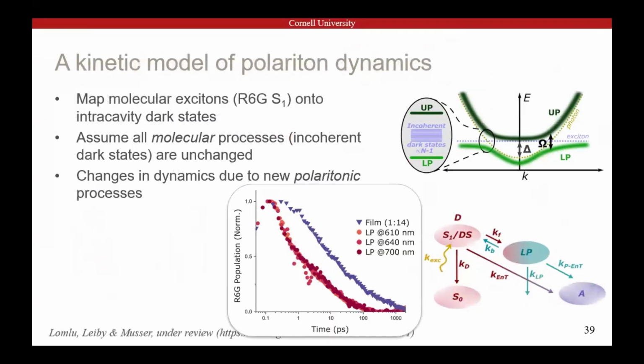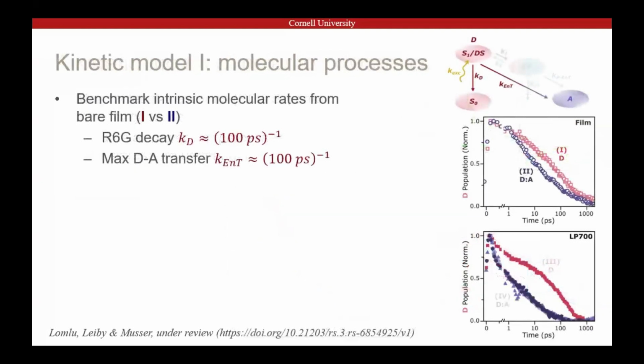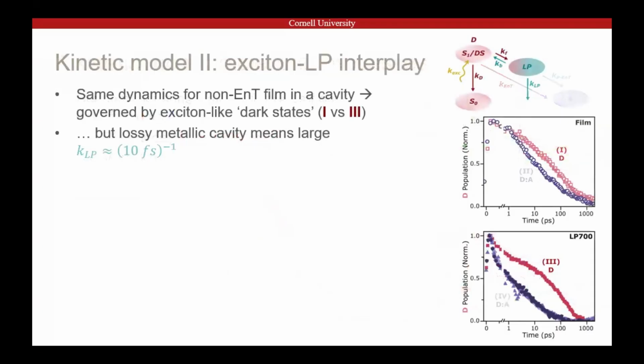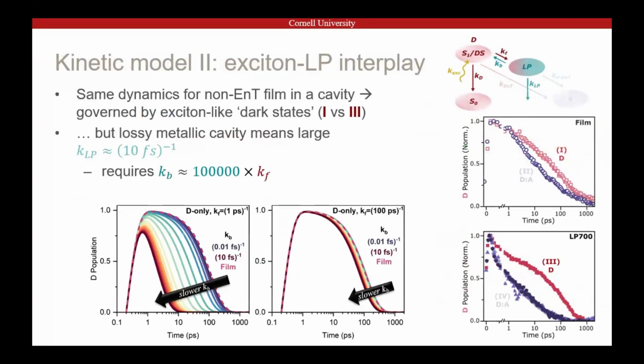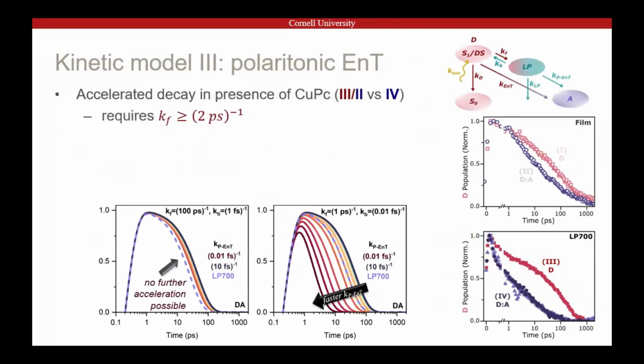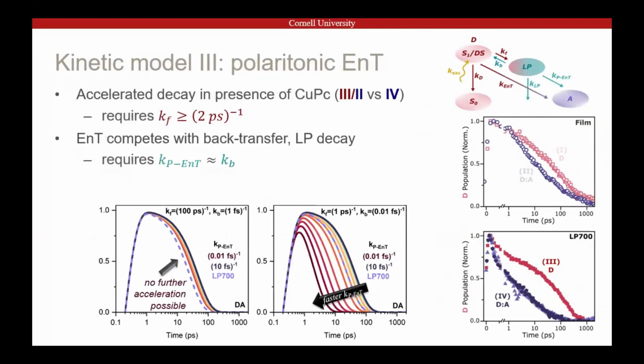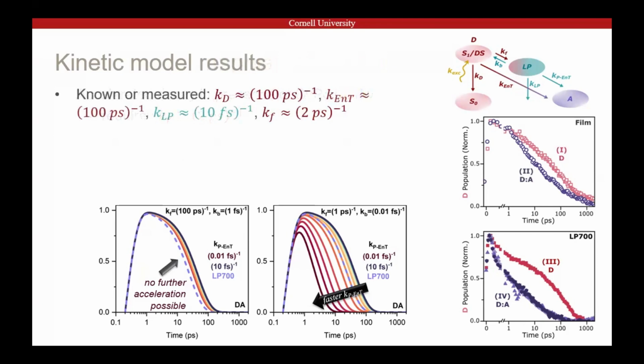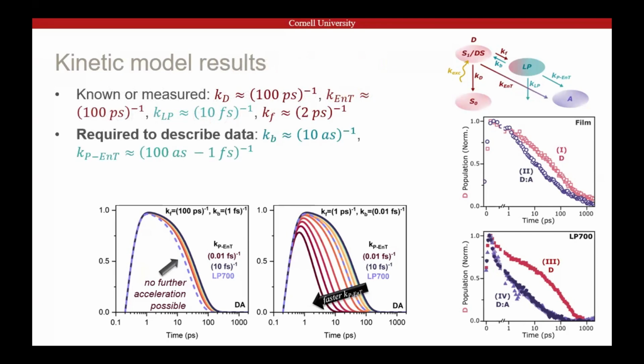With this model, we can put together all of the processes that happen in our films, whether it's relaxation of the dark states or the bare excitons, direct transfer to the acceptor, and then there's equilibrium between dark states and polariton communicating with the acceptor. I'm happy to talk about these more, just to say we can benchmark all of these rates very carefully from our reference experiments with low acceptor or cavity 3, which sets up some really fundamental constraints that require basically these processes, the back transfer, the lower polariton decay, and the polaritonic energy transfer all have to be competitive with each other, which sets up a really strong constraint on the photophysics of the system and leads to some wildly uncomfortable numbers, which I'm just going to leave you to ponder.